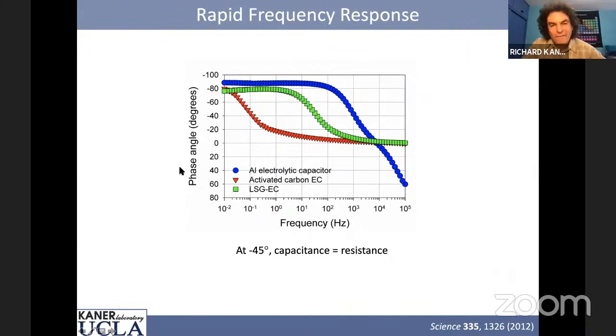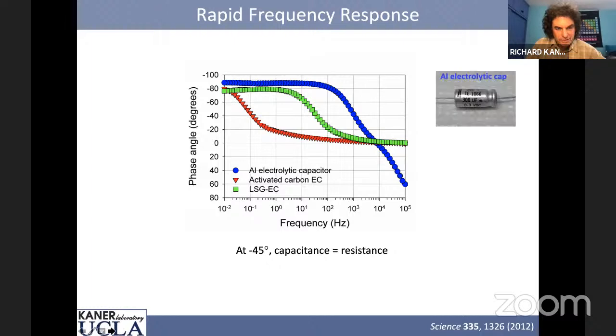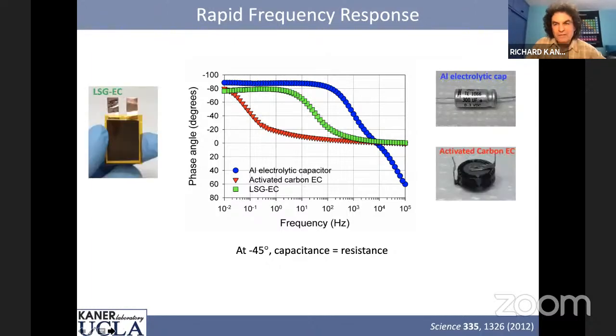Now we can look at how fast these materials are by looking at the phase angle as a function of frequency. And we can compare these to an aluminum electrolytic capacitor, to an activated carbon supercapacitor, and to our own material. And what you'll see is that the activated carbon supercapacitors have a time constant of about 10,000 milliseconds. When we go to our laser scribe graphene, we're over 300 times faster. So our material works quite fast.